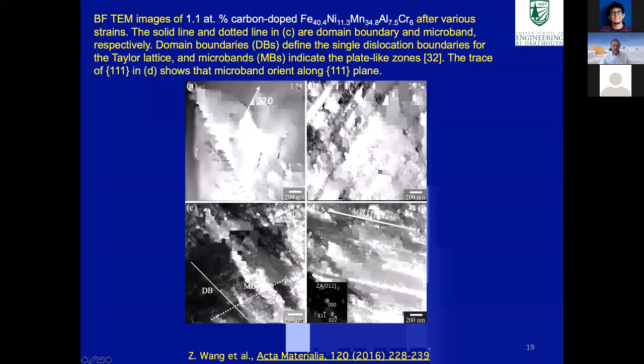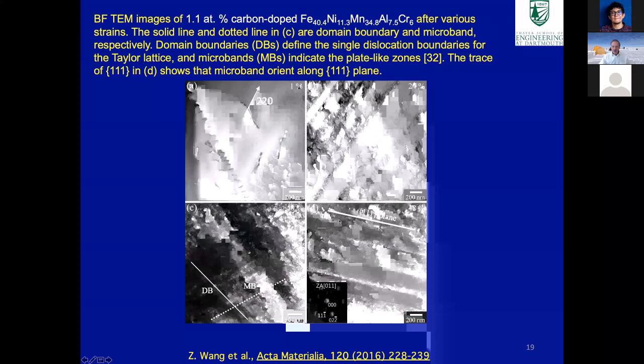And you can see here, by the time you've added 1.1 atomic % carbon, you've got a very planar slip structure, and these microbands aligned along {111} planes. And we think these microbands are the reason that we get both a high work-hardening rate and the high ductility.